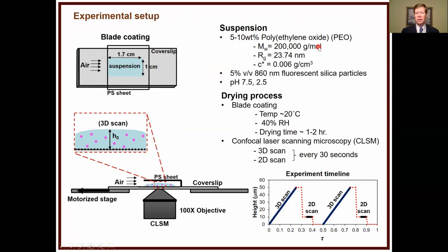They use an edible PEO, which has a relatively high molecular weight, which you can change to control viscosity for coating, but most of the time you're thinking about drug delivery rate and dissolution. And so we've just picked an off-the-shelf commercially available polymer. It has a polydispersity certainly to that molecular weight. And we're going to be at 5% by weight PEO or 10% by weight PEO. And all those concentrations are well above the overlap concentration right from the bat.